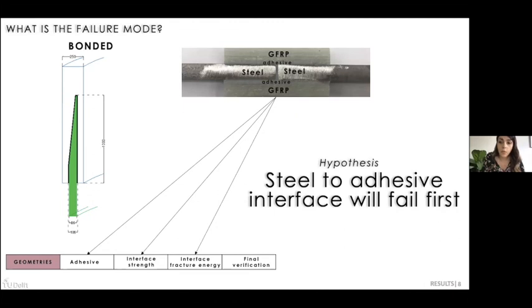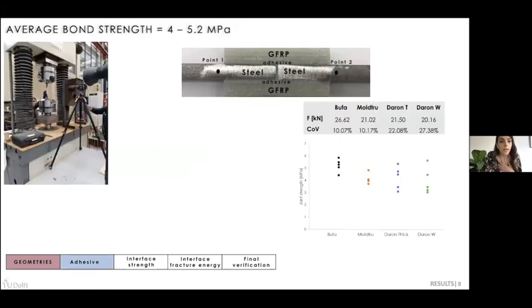Performing these tests and then modeling the results would give me an answer to 3 questions. First of all, what kind of adhesive to use? Then, which is the failure mode to be expected? And third, what are the interface properties that I should input to my large-scale model? Answering which is the best adhesive was the easiest task for me, because the only thing I had to do was test 4 different adhesives, and the one that performed better was the one that was selected.